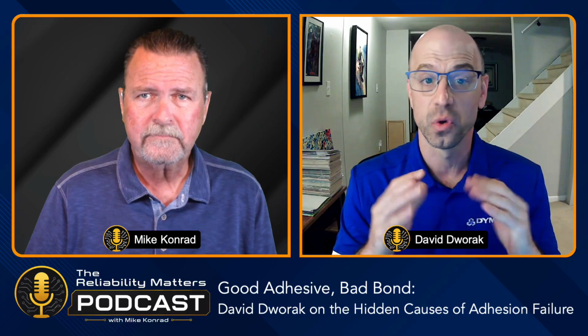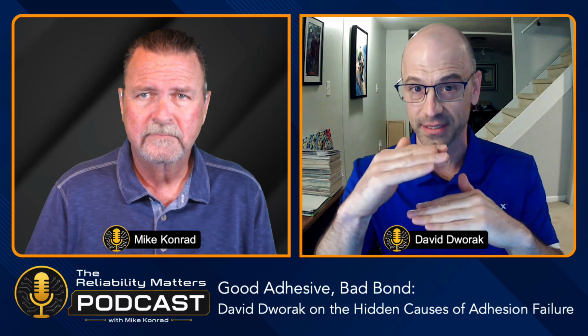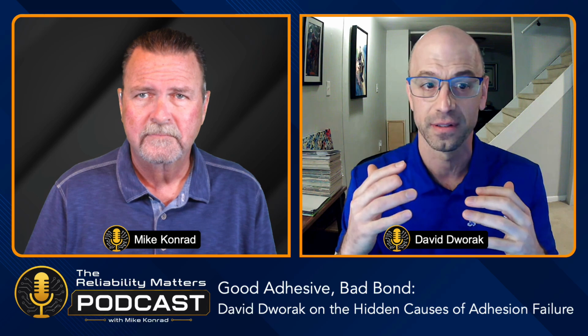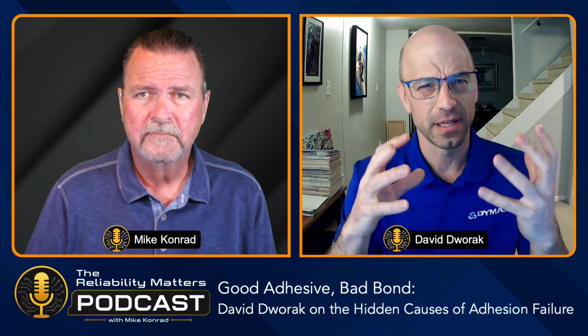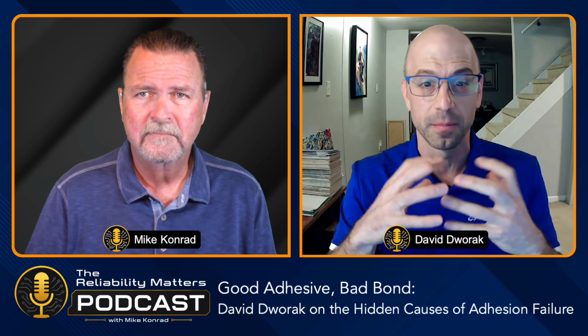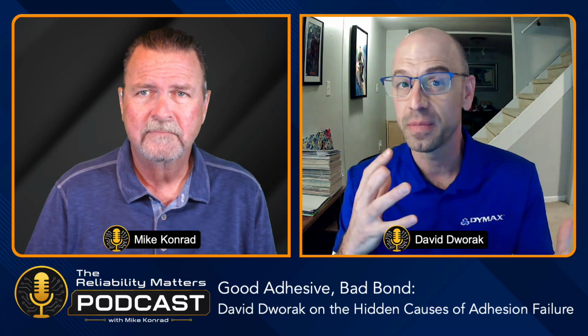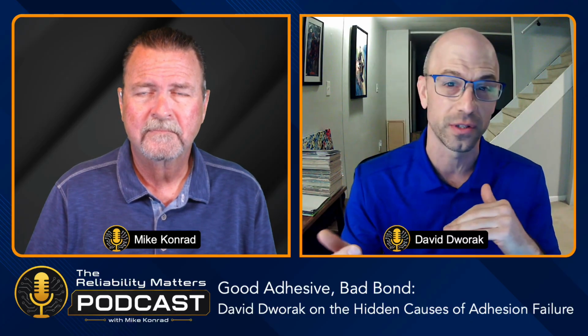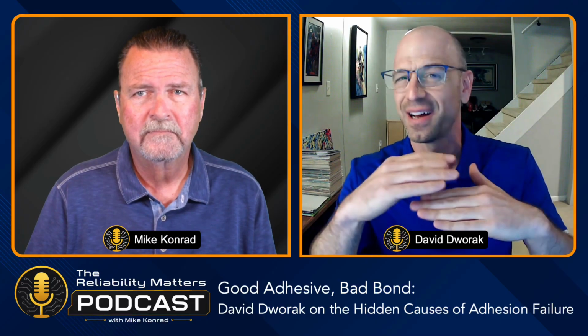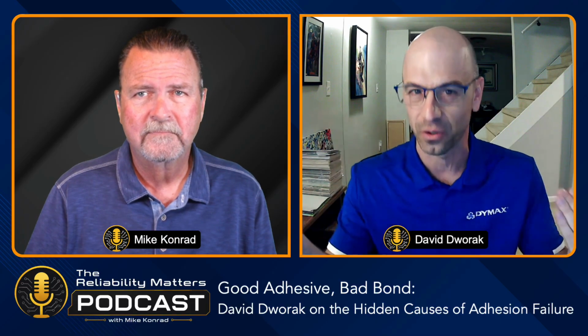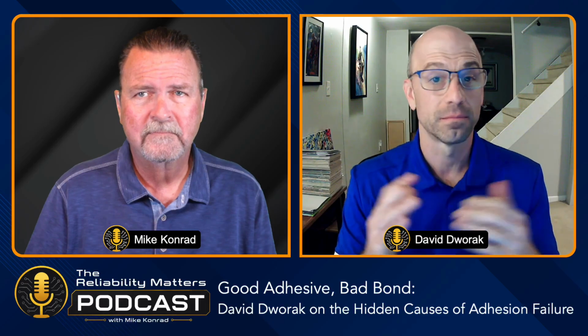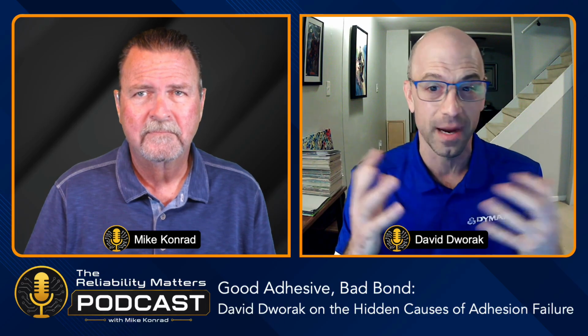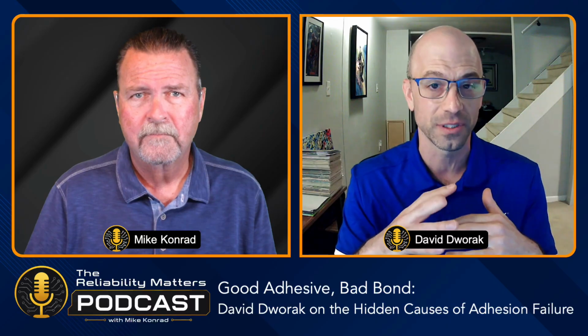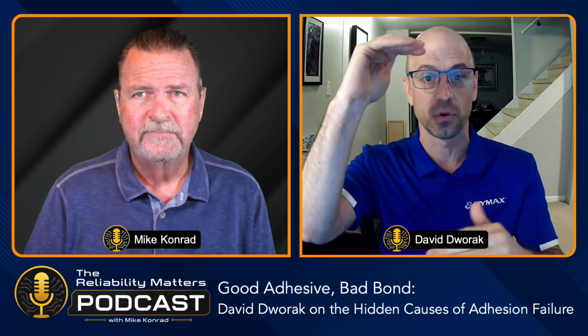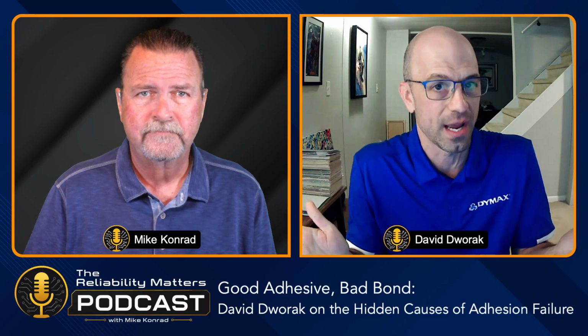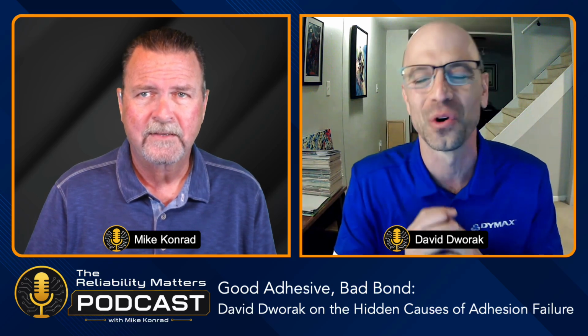If the adhesive tore apart and stayed on both substrates, that's termed cohesive failure. And this tells you the adhesive adheres well to both substrates, but the bulk polymer failed. And this could be due to maybe you over-cured or under-cured the adhesive, like we're talking about. Maybe it's 80% cured, enough to get it out the door and hold together, but under stress, it breaks apart. Also, the adhesive breaking here might be okay if the force that it broke at was above your requirement. That might be okay. I just want to say it's not the end of the world if that happens.